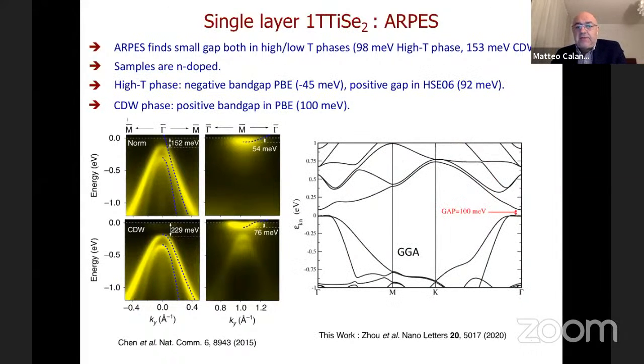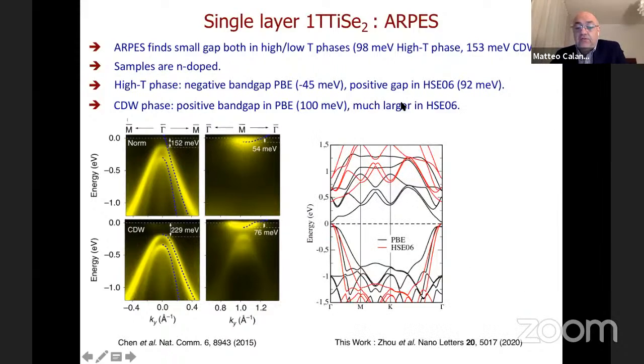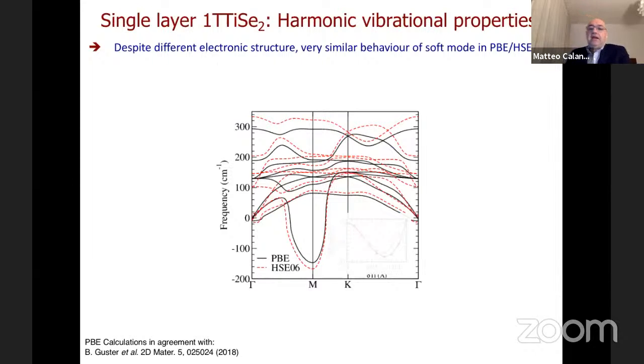And if you go in the charge density wave phase, at the GGA level, you have a 100 millivolt gap. This is plotted in the charge density wave phase, so the gap is underestimated. But if you do HSE, the gap is strongly overestimated. In the bulk, the structural properties and the gamma phonons are perfect with HSE06. But on the contrary, for the electronic structure of the charge density wave, HSE06 tends to give a much larger gap, of the order of 0.3, 0.4 eV, so approximately 300, 350 millivolt. Now, what happens if you calculate the vibrational properties?